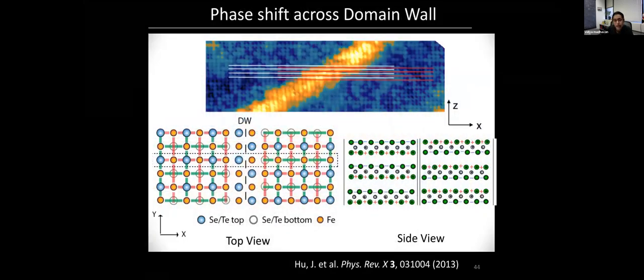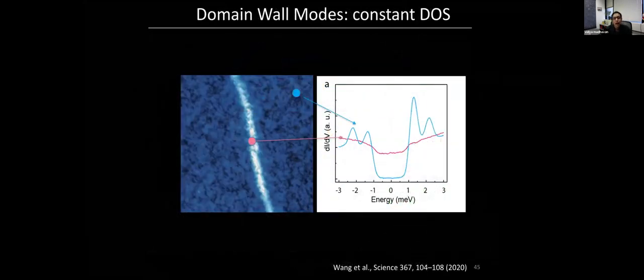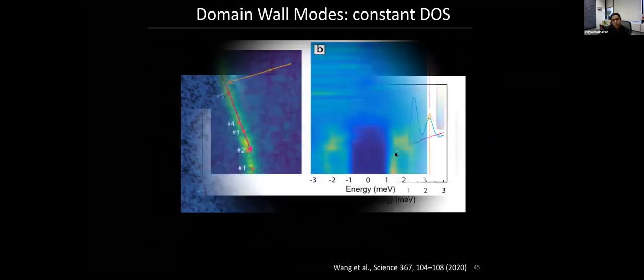So now we can ask, what do we see when we go to such a domain wall? And so here's what we see. Far away from the domain wall, we see a nice superconducting gap with actually zero density of states. And if you go to the domain wall, you see the gap, but then you see this flat density of states inside the superconducting gap. So the superconducting gap is filled up. You have a finite density of states, but it's a flat density of states.